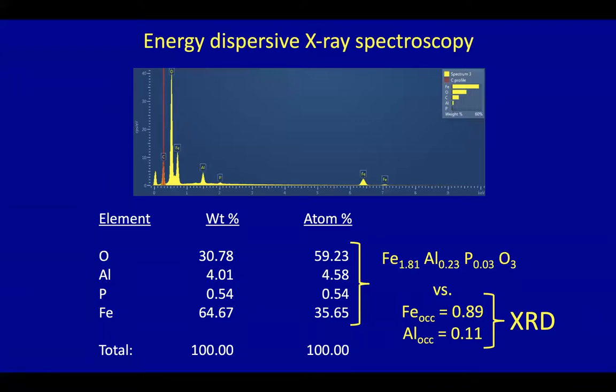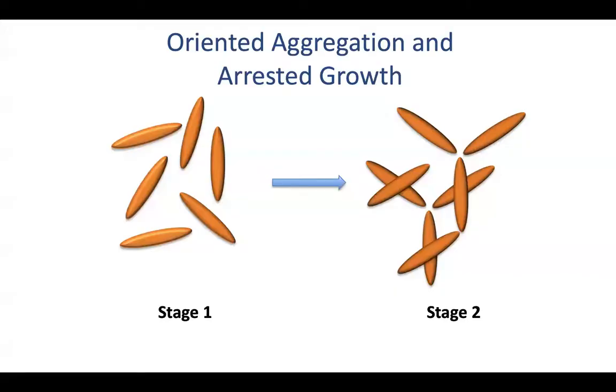So the Al occupancy there is 0.11 times 2, that would be 0.22. And that's a pretty good match for what we found with the energy dispersive X-ray spectroscopy. And the iron, likewise, when we double it, matches very closely to what we got from this EDS data. So in other words, there's really very little doubt that these little spindles are hematite that contain iron, aluminum, and phosphorus impurities.